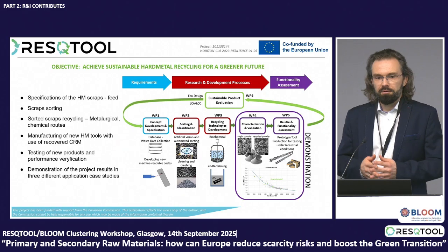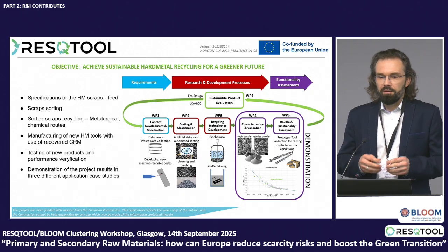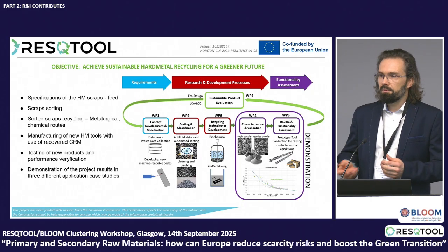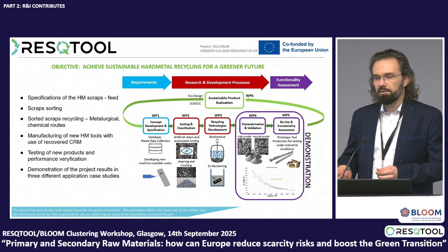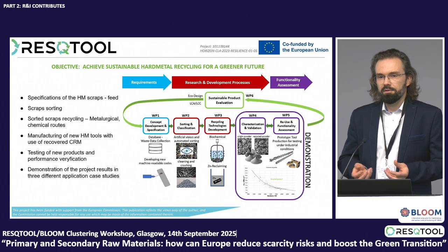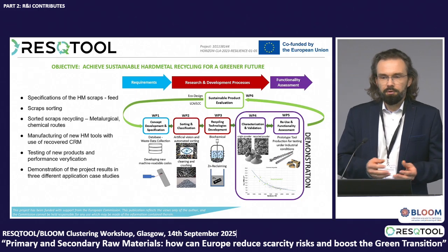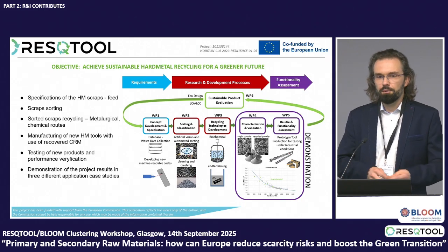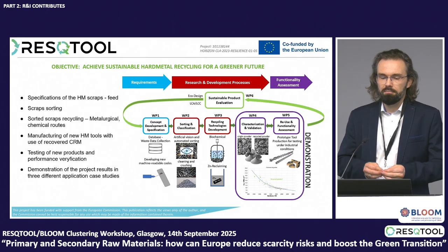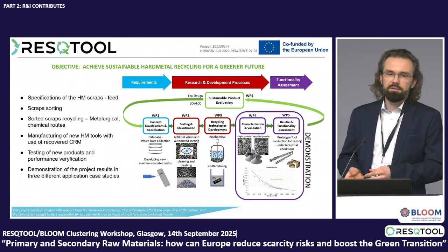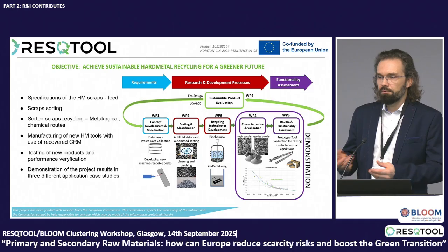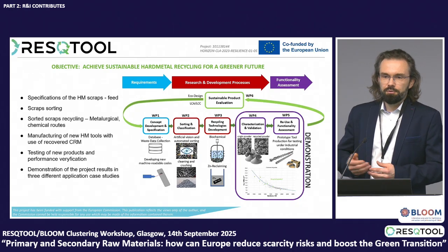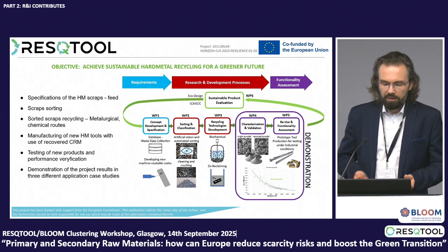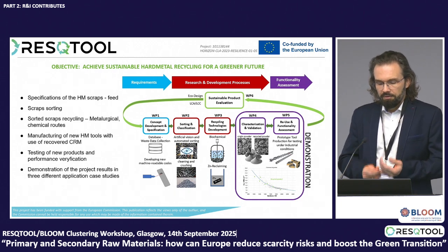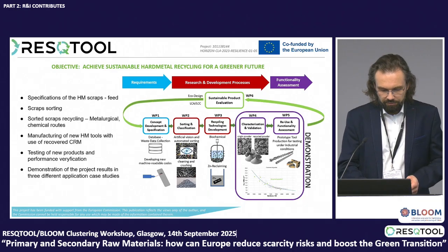This is very critical, because when you downcycle the scraps, for instance, as a steel additive, because these are the techniques for today, we are losing the carbides. When you add titanium carbide into the steel for high quality steels to increase the titanium level, then you lose the carbides, which is very high loss in terms of CO2 emissions and other factors.